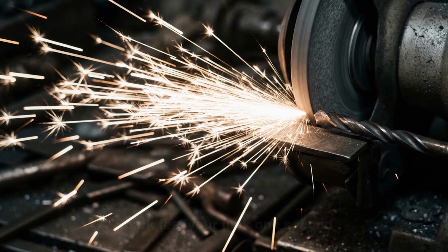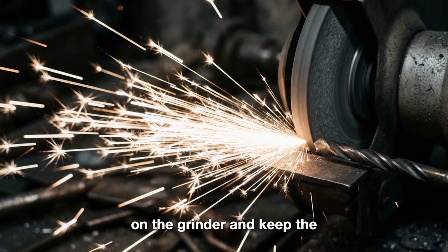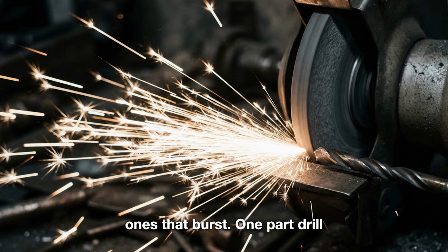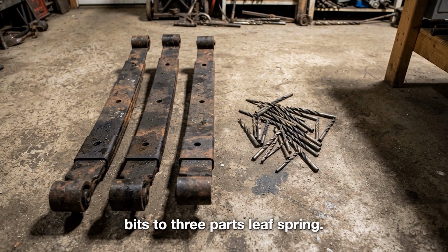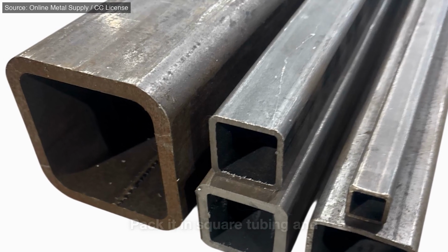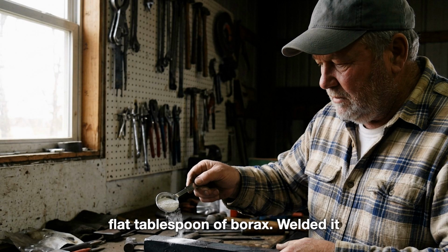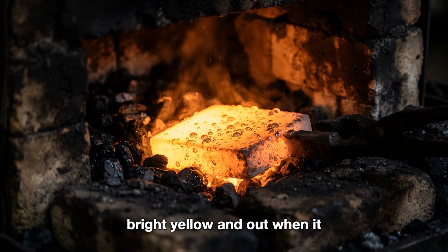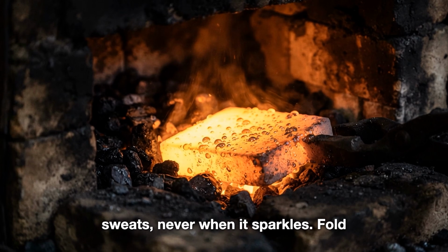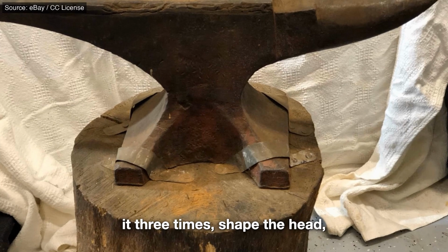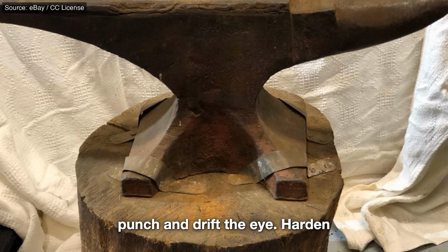The steps. Spark test your junk, 1 second on the grinder, and keep the ones that burst. 1 part drill bits to 3 parts leaf spring. Pack it in square tubing and cap the ends. Flux with a flat tablespoon of borax. Weld it at bright yellow, and out when it sweats, never when it sparkles. Fold it 3 times, shape the head, punch, and drift the eye.